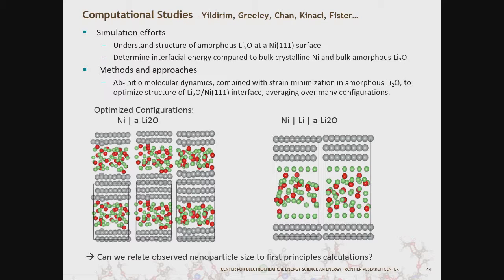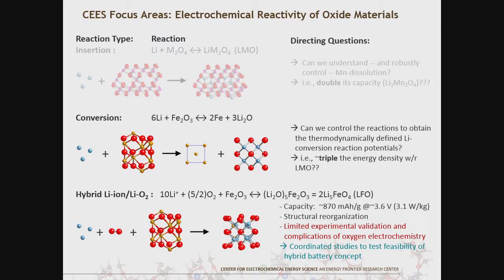We're looking at the disordered interfaces between nickel and amorphous lithium oxide to try to understand mechanistically what these things are, and whether we can get a correspondence between the energetics calculated from these computational approaches and the actual critical nucleus size and nanoparticle size we can see experimentally. So we're trying to use the simple morphology of these materials to dig down and get a better understanding of what's going on.